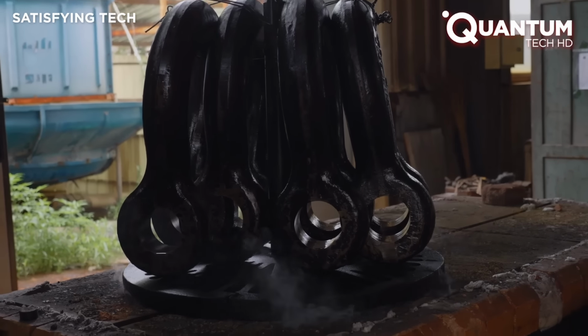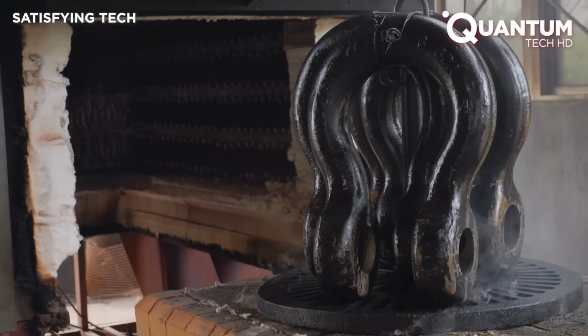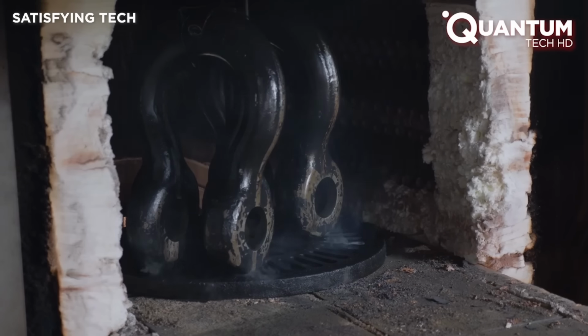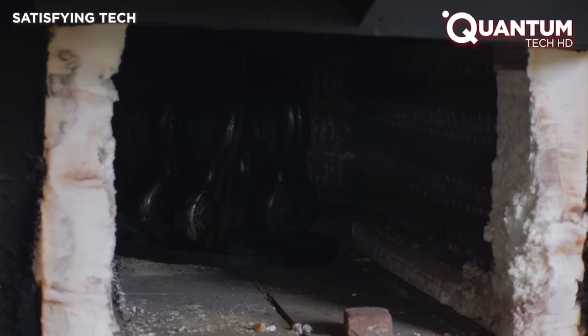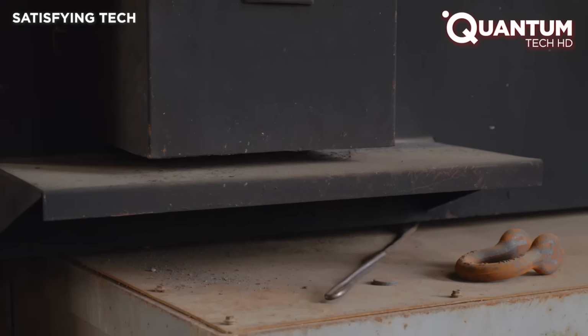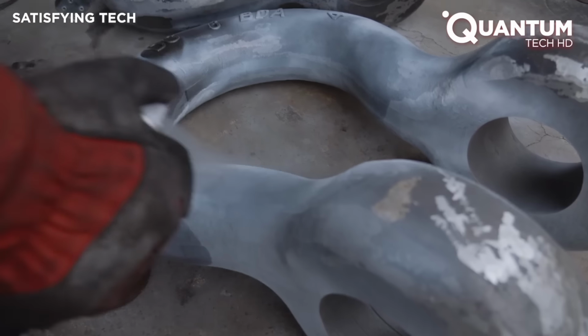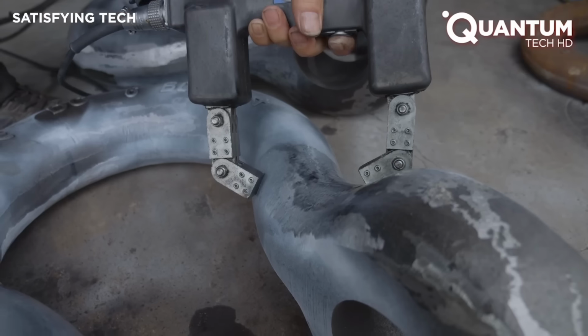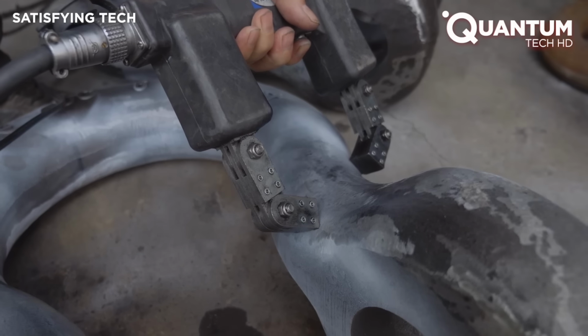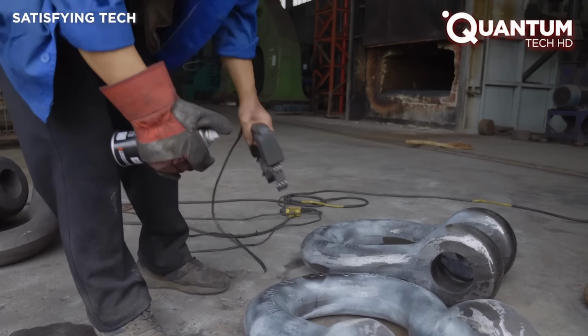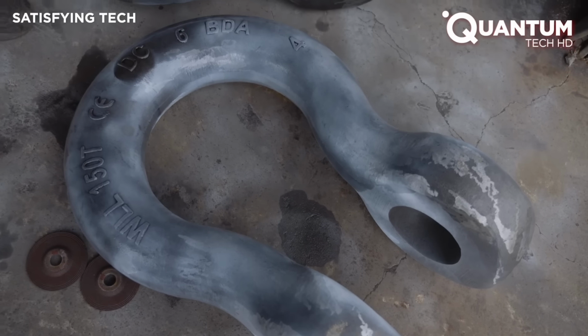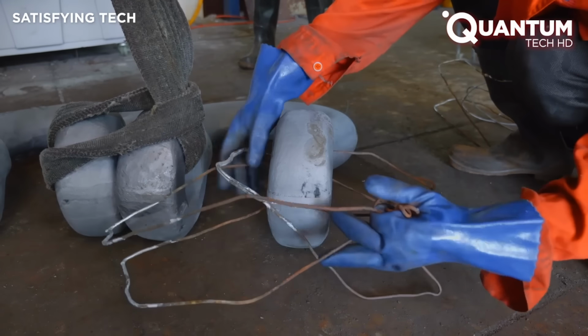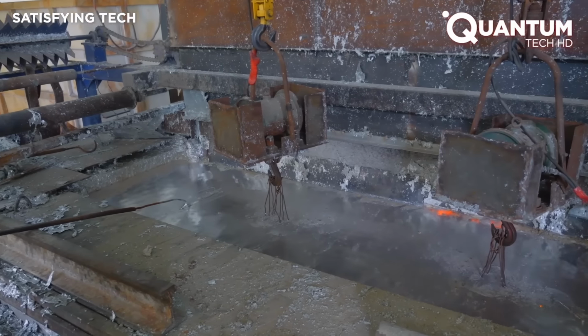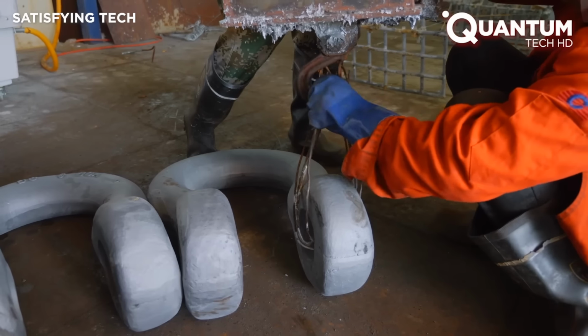The pieces are placed in a second furnace for several hours to reduce the fragility of the steel, giving the shackle the ideal combination of hardness and toughness. Immediately afterwards, they undergo a magnetic particle inspection, a process that uses magnetic fields to reveal cracks invisible to the human eye. The test is passed, but one last threat remains: corrosion.